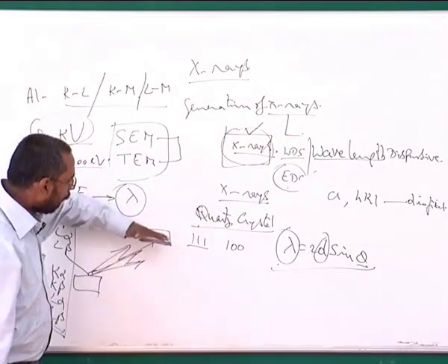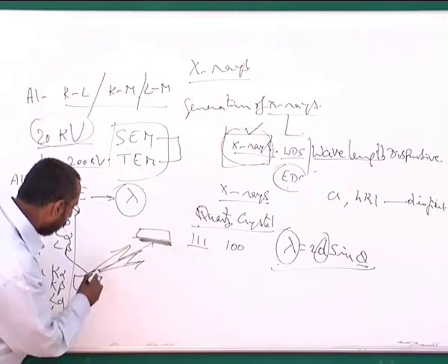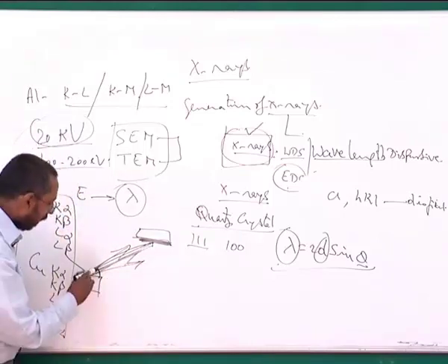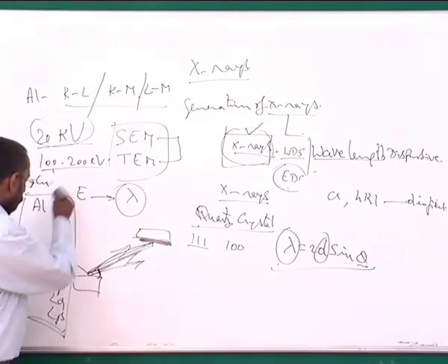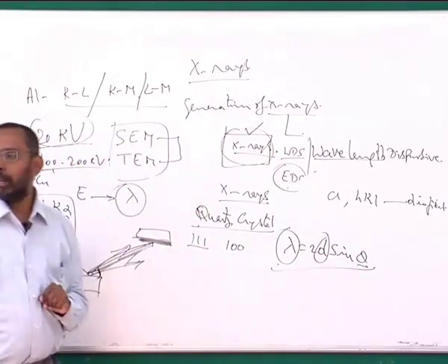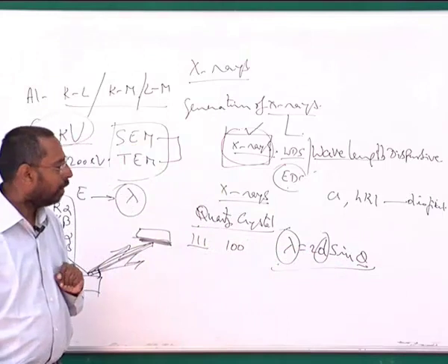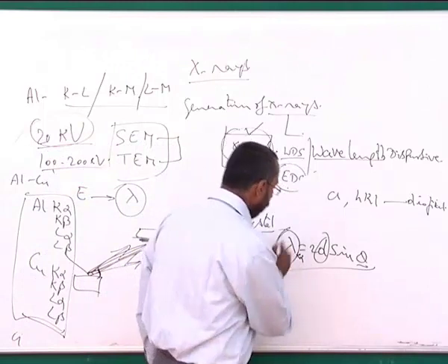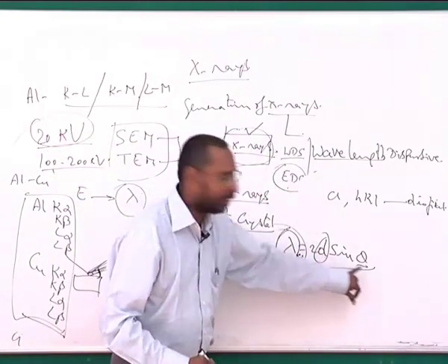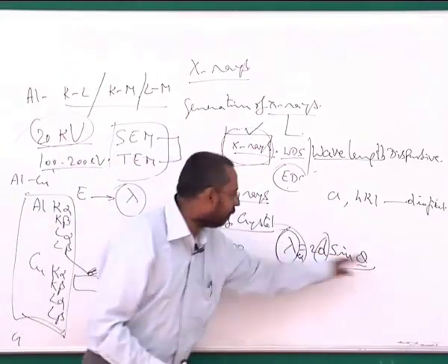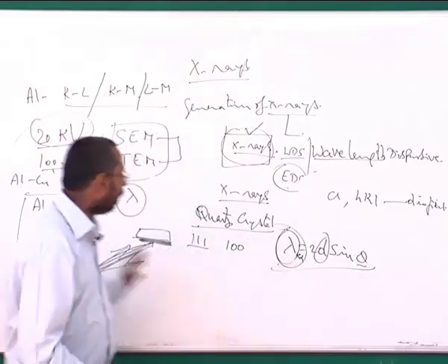So if I keep this crystal at a particular angle from the surface, and fix this angle, then among all these, only some particular radiation can match. Out of these 8 radiations, let's say this is copper K alpha radiation. For a given lambda, once d is fixed, theta is fixed. So until I keep this at the particular angle which corresponds to the K alpha of copper, it will not give me a diffraction at all.